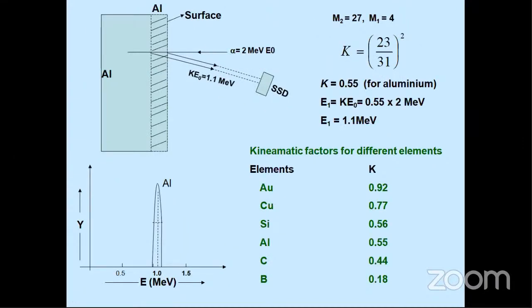So these are the kinematic factors. The incoming energy, outgoing energy, and the energy of the particle are related by the kinematic factor. So E1 is equal to K into E0, where E0 is the incident energy, and the kinematic factor is, say, aluminium 0.55. And suppose 2 MeV is the energy, then scattered energy will be 1.1 MeV. But gold has a 0.92 kinematic factor. So the gold will have a large scattered energy compared to aluminium, which will have about 1 MeV.